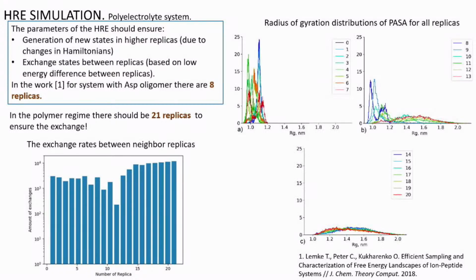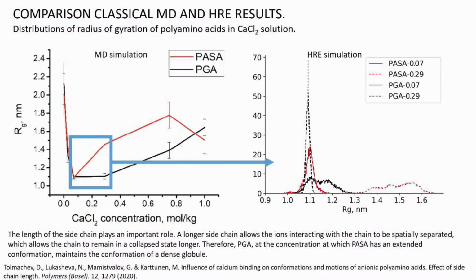So here we can see the distribution of radius of gyration for every replica in one of the simulations. You can see that new states appear in each replica, and in higher replicas the radius of gyration can have a very wide distribution. So we have new states, and we have exchange between different replicas. So our method is working. So let's go to the results.